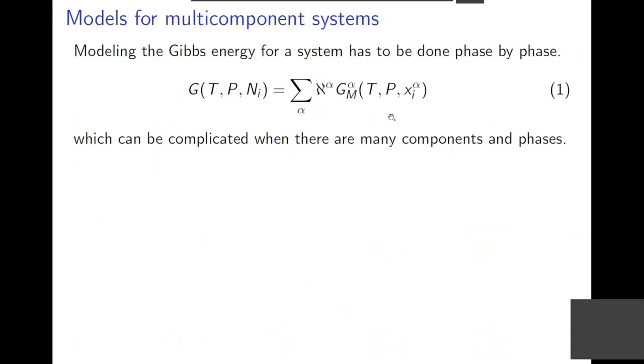Then in order to model the system, the first thing is that you separate each phase. So each phase in the system, different solid phases, gas phases, the liquid phase, you have a model for that, and then you have a different amount of the phases. And summing up all of that for the stable phases will give you the Gibbs energy for the system. And if you have many components, this can be a bit complex.